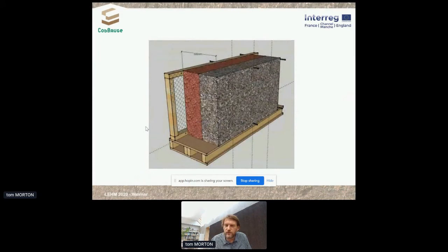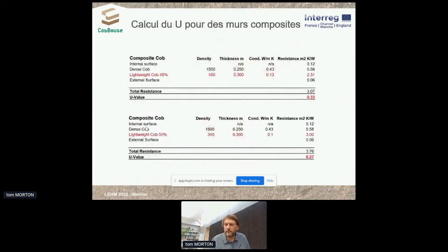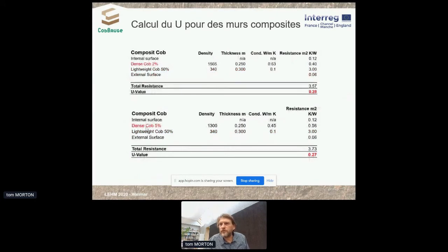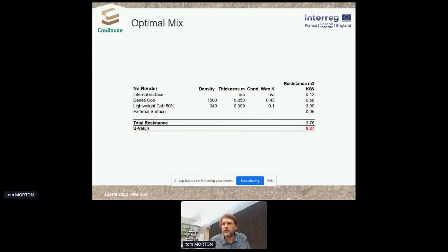And this took us to the conclusion that we needed a composite material of 2 layers, one with a dense material to take the structural load and the other a light material to provide thermal performance. We looked at mixes of composites of 2 layers, here varying the thickness and the density of the lightweight cob to fine-tune the result down to the 0.3 U value within a 550 millimeter wall. And here we're looking at the amount of fibre in the load-bearing cob and how this affects the density. So the optimal mix was a wall of 550 millimeters thick with a dense cob layer at 1500 kilos per cubic meter and light cob at 340 kilos per cubic meter, achieving a U value of 0.27.